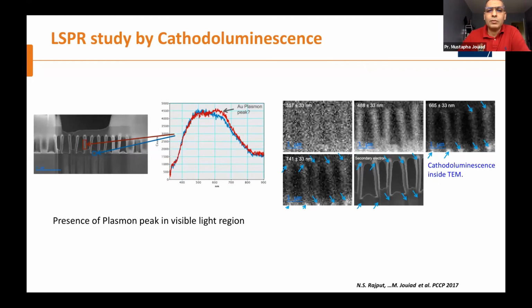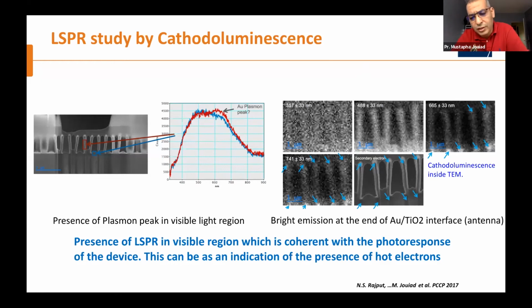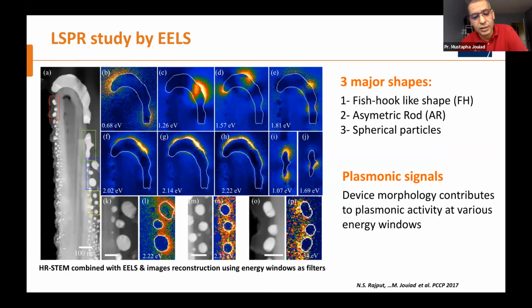So next, this is a summary of it. We have a presence of LSPR, and it is in the visible region, and it is coherent with the photoresponse we just showed you. And this is an indication that we can create hot electron that can be injected in the conductive band of titanium. So this is another deeper insight about this LSPR. What we did here is high resolution microscopy combined with another technique called Electron Energy Loss Spectroscopy. This shows that we have this excitement everywhere in our new shape that we call fish hook-like shape. And we have another shape with actually an asymmetric rod.